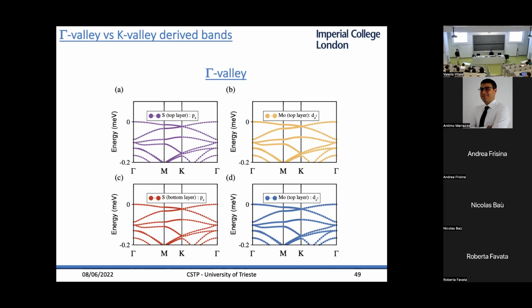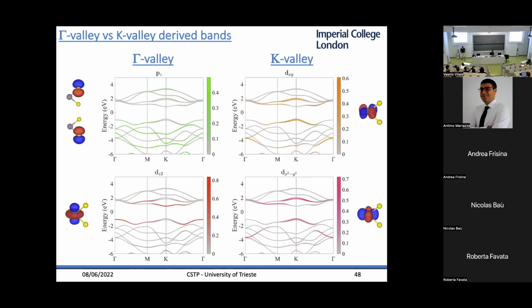If you put in, for example, rare earths, it starts to get more complicated, I think. Well, it depends on what kind of bands you're interested in. The states from the monolayer that really contribute to the Moiré bands are those close to the Fermi level. So in theory, you could have a very good tight binding of a single band, right? But that's quite hard to do, and you can do an empirical tight binding, but then you lose control of the meaning of these parameters. Here, everything comes from the hoppings of these orbitals.